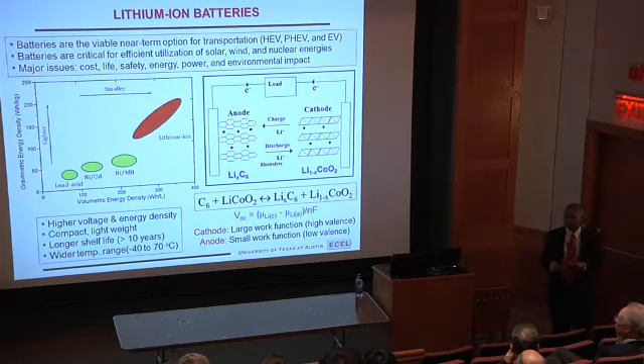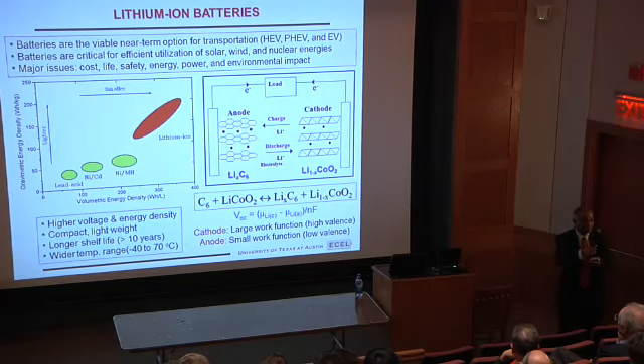Third, when you do this, the material should maintain these kind of layered structures intact for thousands of cycles. Supposing if it is collapsing or this guy, cobalt, migrating from that to here, when you create a lot of vacancies here, that will decrease the amount of material which can store the charge, so capacity will fade over time. So you have to have good reversibility.